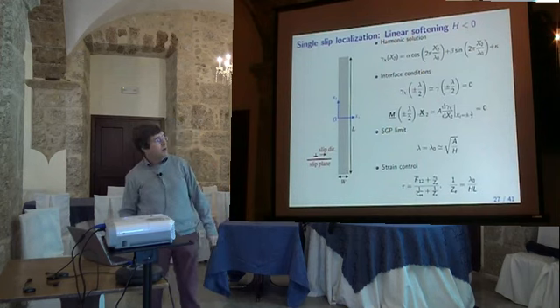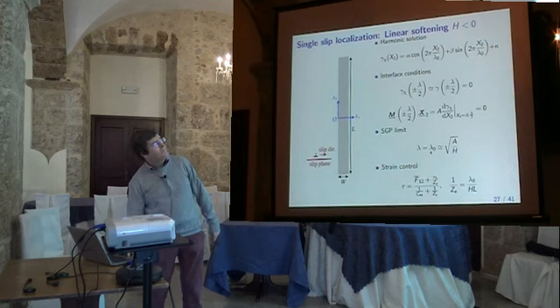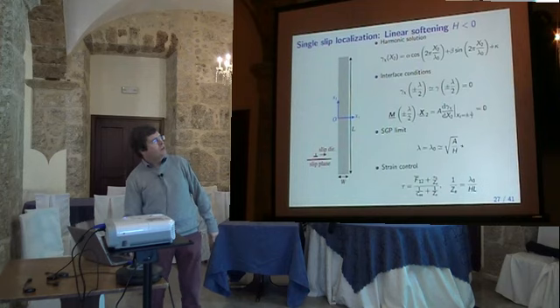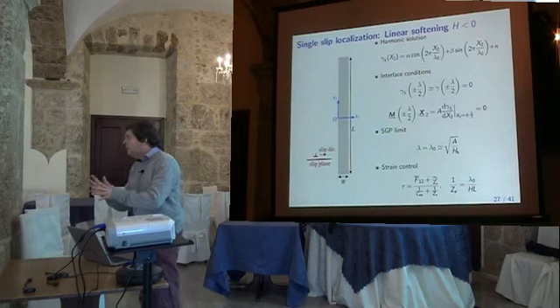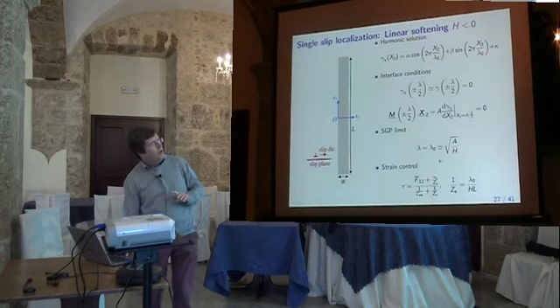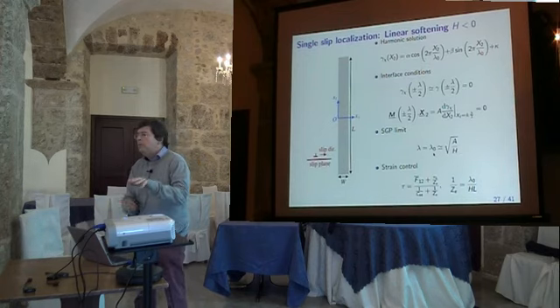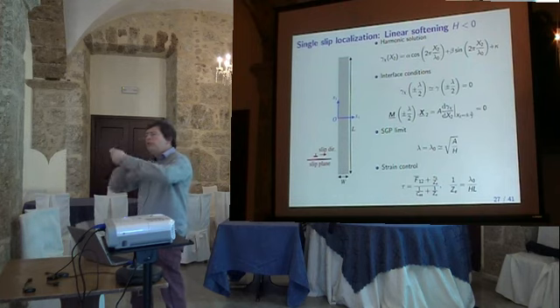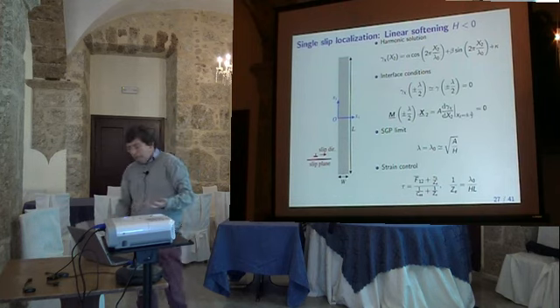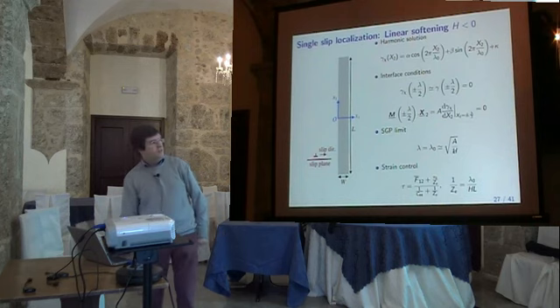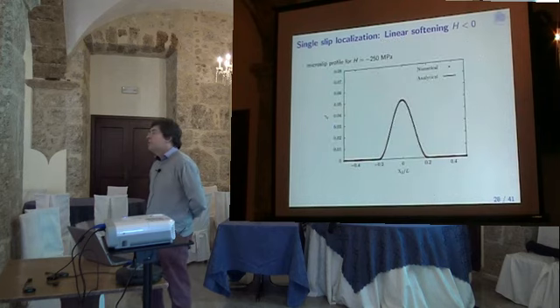And then again you have the same intrinsic length, which essentially is the ratio between A and the absolute value of H, because this is negative here. So you see it's very clear how it depends on A and H. This length, lambda 0, is the length of the shear problem. If you change the boundary condition or the loading, you will have a different solution. It will always be a function of A and H in that case. So you find this, and if you look at the profile, this is a cosine function simply, and this is a localization zone.